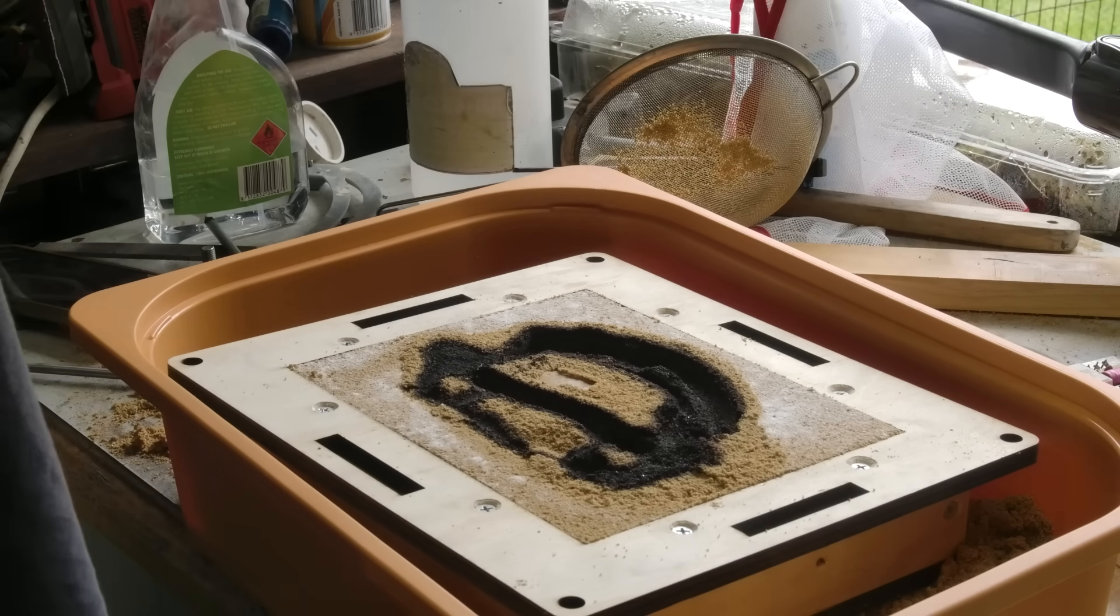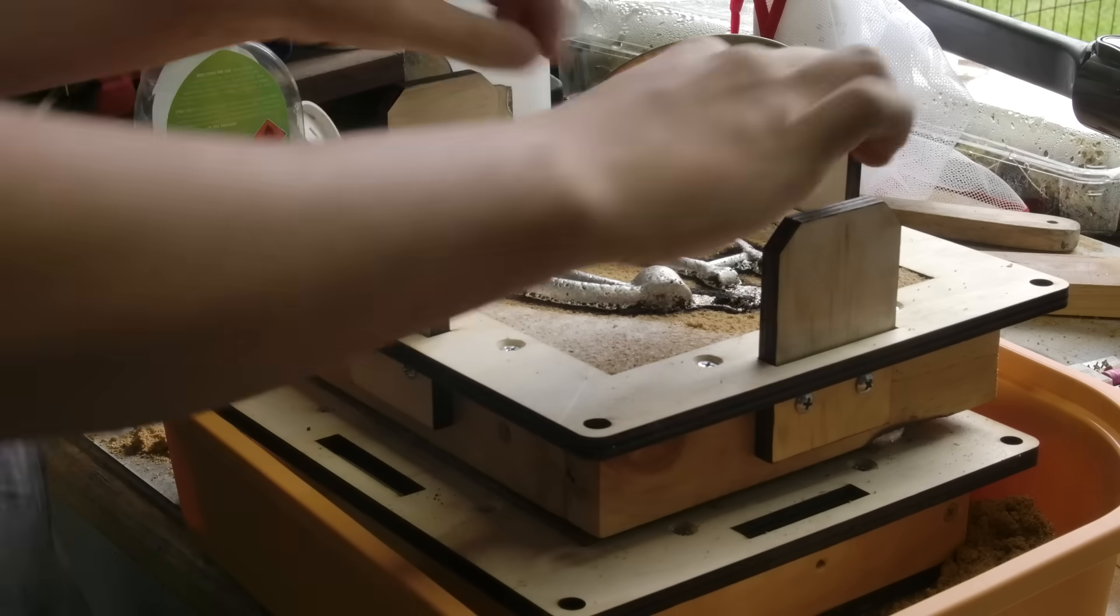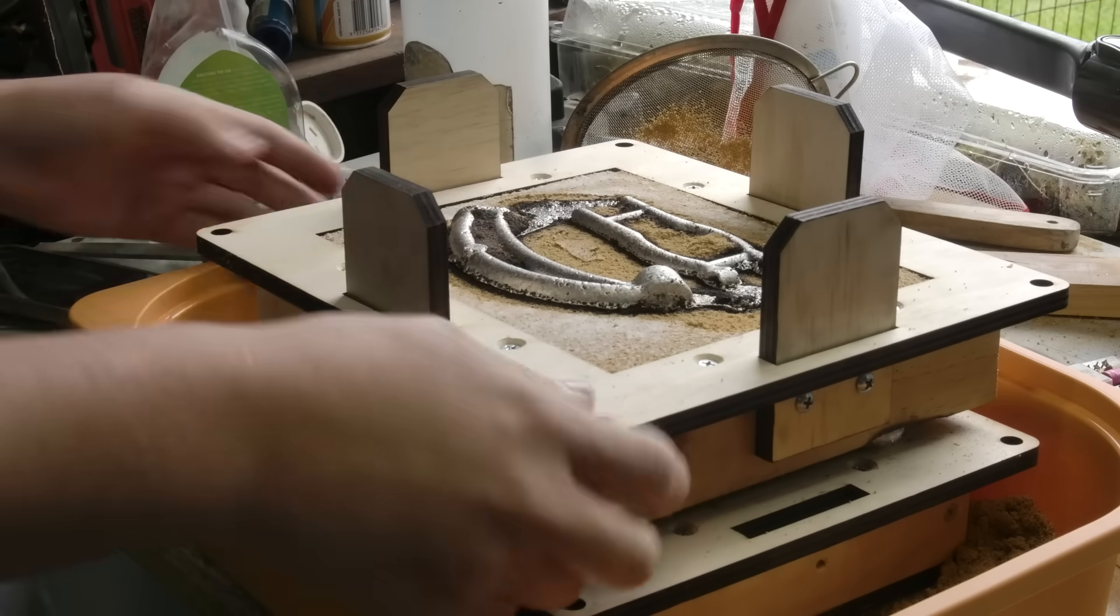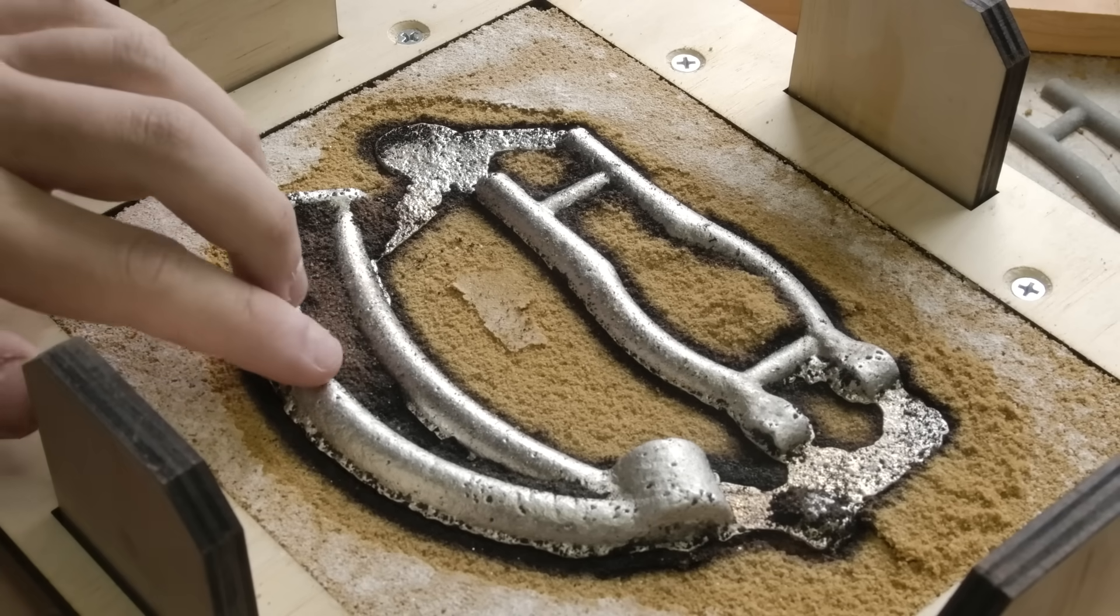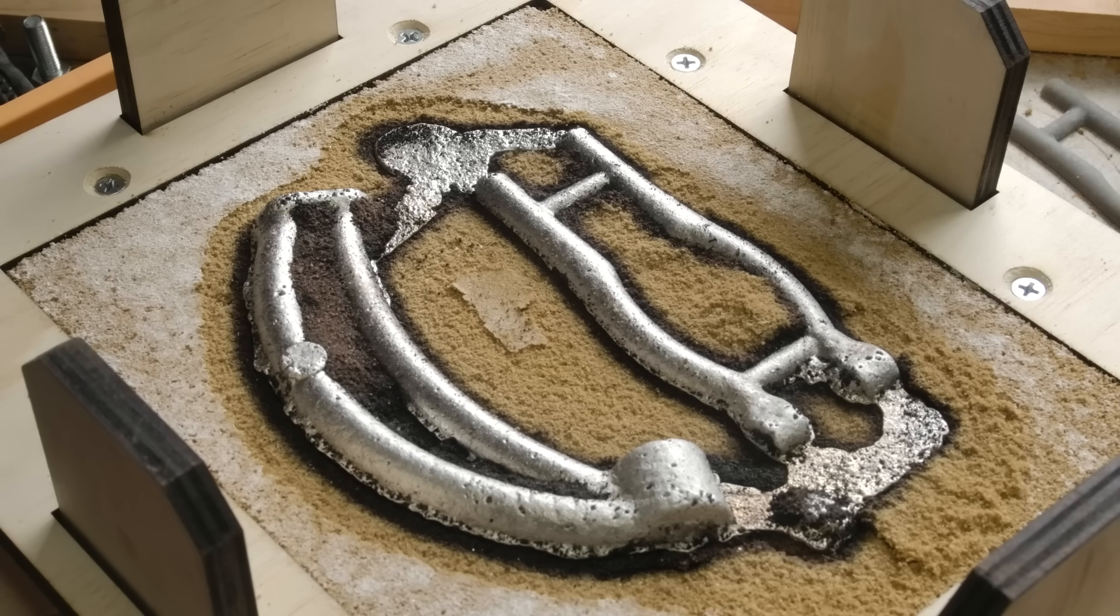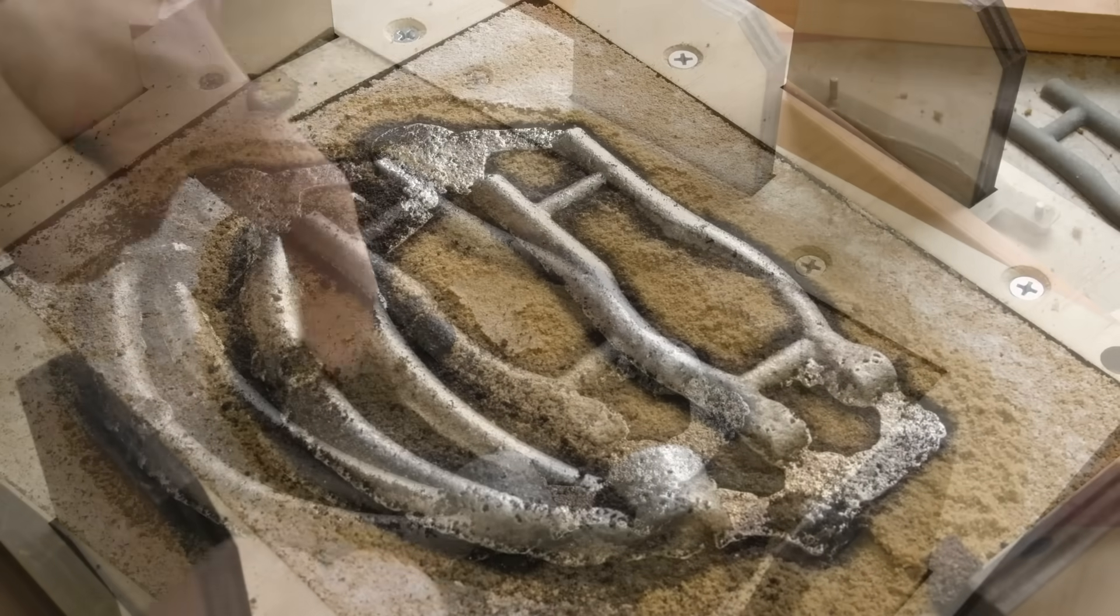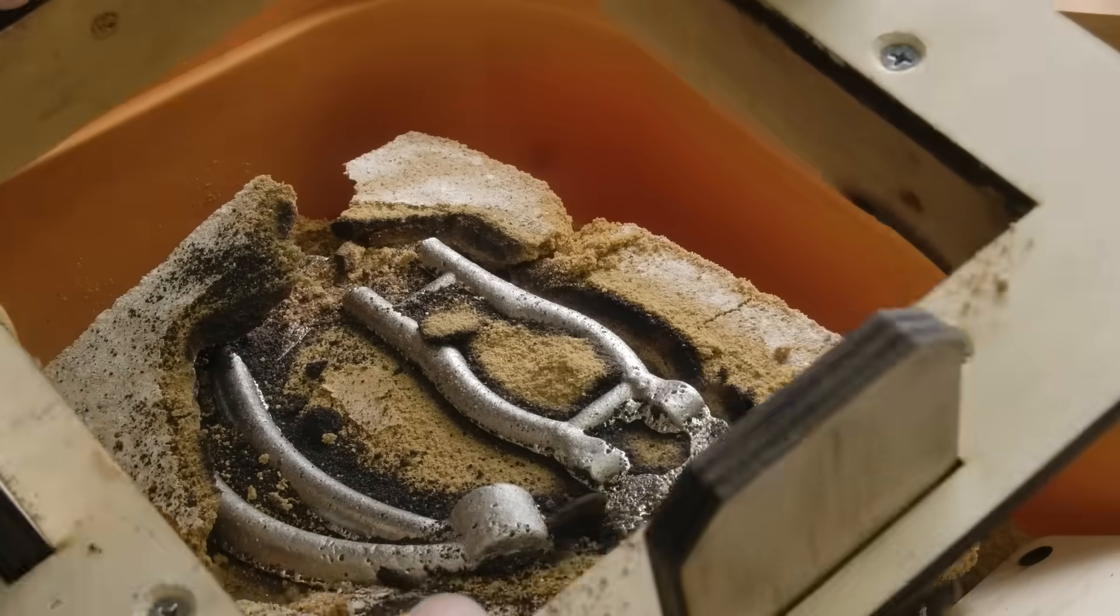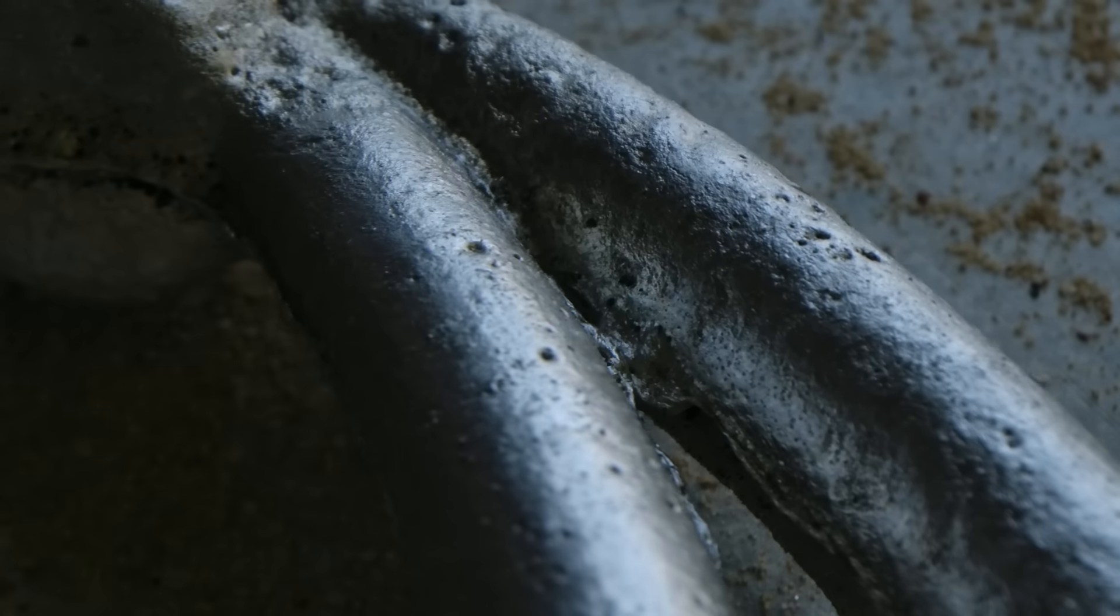Okay, well, all the sand's burnt. Oh, there's a lot of bubbles. But it filled completely. I think I can work with this. I was going to paint these parts, so... Yes, interesting, there's a lot more bubbles in the part this time. I think that's because I wasn't keeping the sprue full enough. For this project, the parts are good enough. They will just require a lot of post-processing.